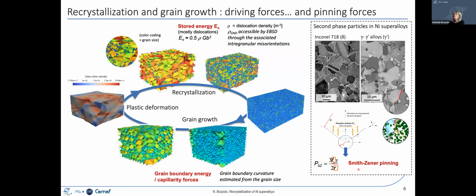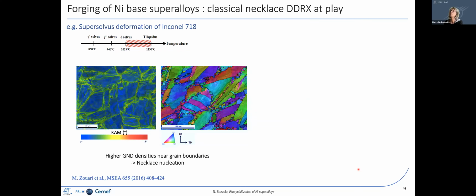Now, if we go for a typical forging of a nickel-based superalloy, starting first in the supersolvus domain. So in the supersolvus, the second phase particles are dissolved. So we have a single phase material. Here you can recognize grains which have been deformed. This is a local misorientation map which has been obtained with EBSD, and the color is related to the orientation gradients you have at the local scale between one given point of the map, or pixel of the image, and its neighbors. So as you can see, you have steeper orientation gradients near the grain boundaries.